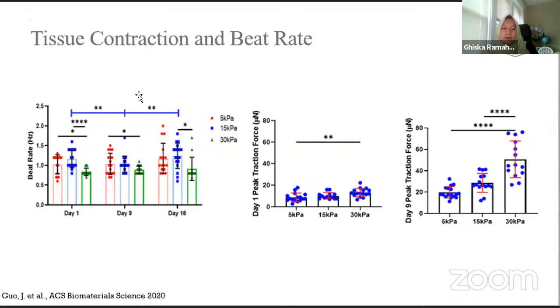And then what we can see here, by modifying the stiffness of the substrate, like under the tissue, we have the PDMS substrate, and we modify the stiffness to see differences in traction force and sarcomere and the beat rate. So what we can see here from this graph, in day 16, we get a higher average of beat rate, and also from the traction force in day 1, we get higher traction force by having higher stiffness of the PDMS substrate, and it's also expressed in day 9 after the tissue incorporation.